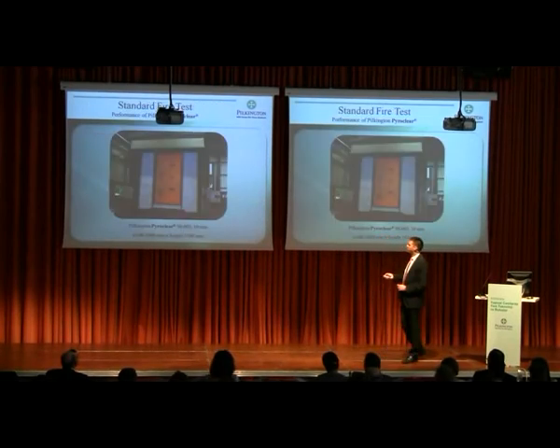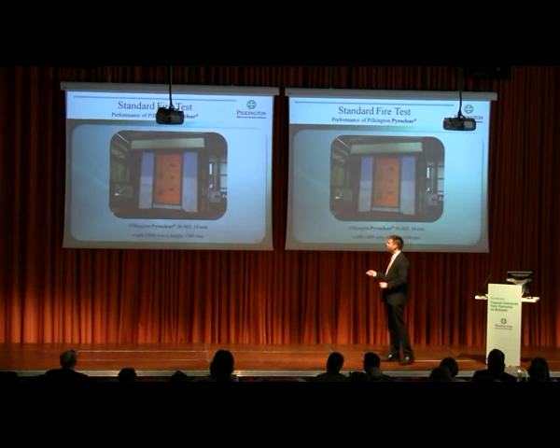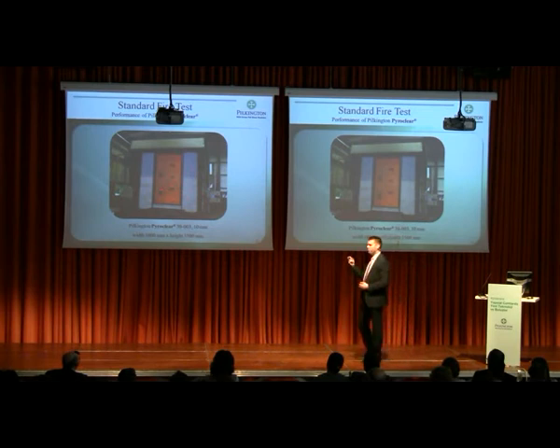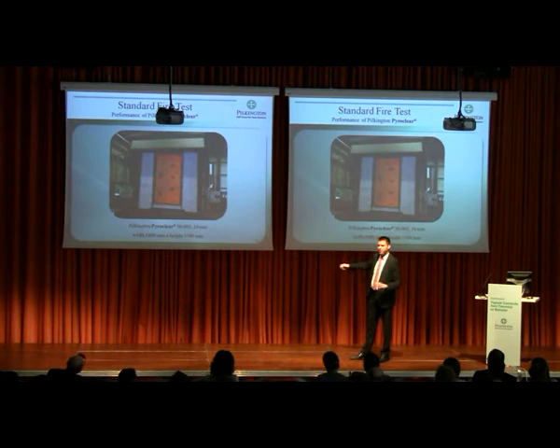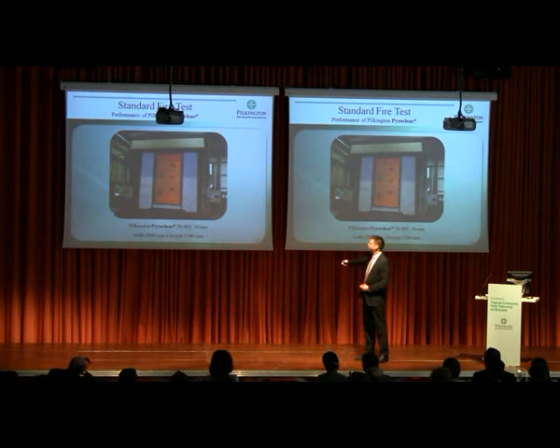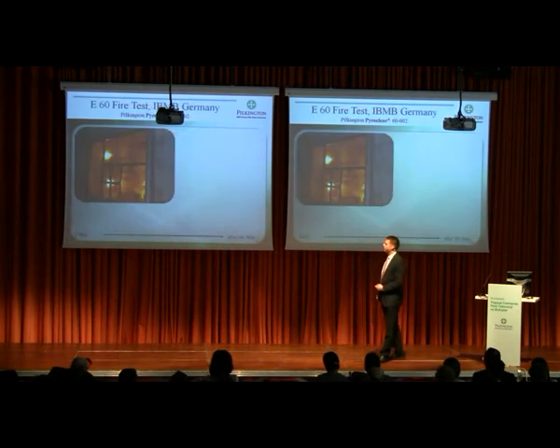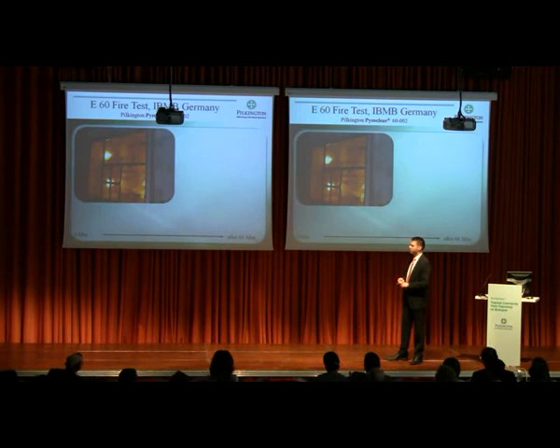In a fire test, for example, it looks like this after 35 minutes. A huge pane, in this case 1.8 by 3.5 meters. The glass is still in place, but you have all the heat radiation passing the pane. There are no interlayers, nothing which reacts, it's just the pane itself which stays for the required time due to the way we produce it. For E60, for example, a typical application at the moment is in Turkey, as I learned.